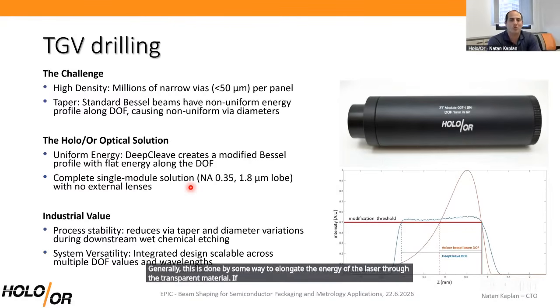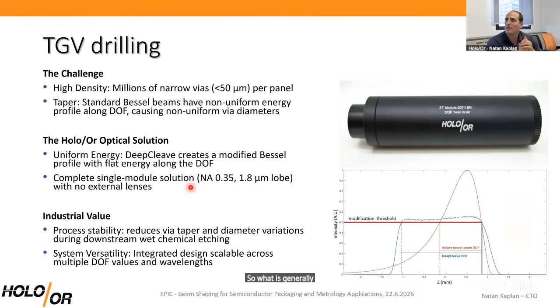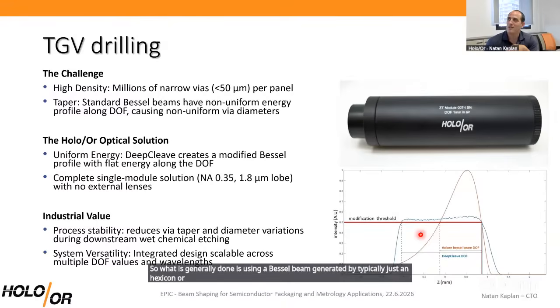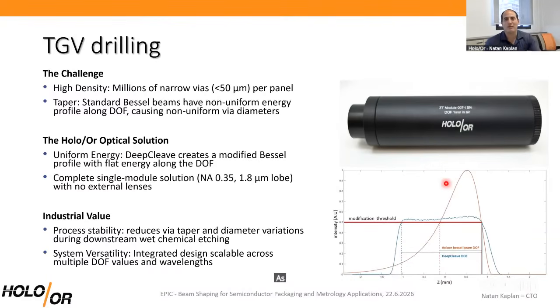If you just try to focus the spot to a spot of 50 microns, you will not reach the energy density necessary to modify the material over the entire bulk. So what is generally done is using a Bessel beam generated by typically just an axicon or a diffractive axicon. But these types of beams do have a good depth of focus and a small lobe over the entire depth, but their energy changes. As you can see here in the graph, as you go to the depth of the material, there is an increase in energy and then a drop in energy.